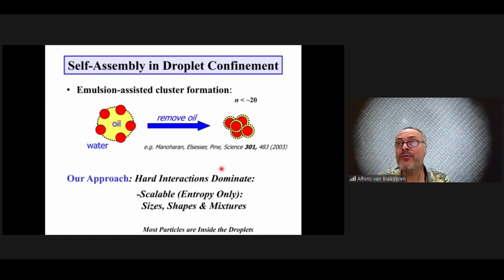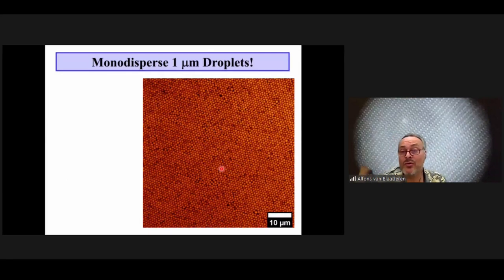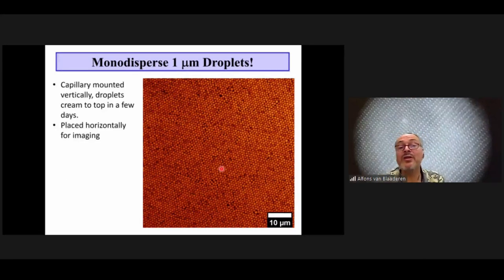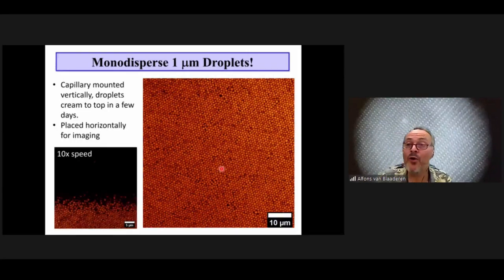What if we make the attractions not very strong? An important scalable property of our self-assembly is that what we do for the self-assembly of nanoparticles, if they behave like hard interactions, is completely transferable if we self-assemble 1 micron size spheres in bigger droplets as well, or 100 nanometer size particles also for optical properties. So if the interactions are not strongly dependent, then we can scale our procedure to all different kinds of length scales.